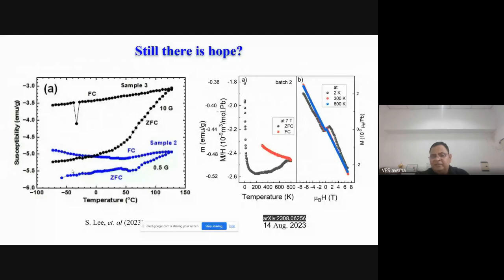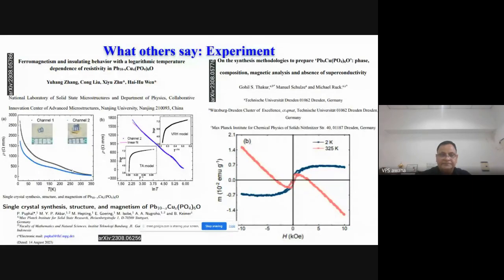In their M-T, M-H, and M by H with temperature, the magnetic susceptibility and moment both are shown. In fact, it's a system which shows diamagnetism. At the same time, it had some magnetic properties at low fields, which if you zoom at plus minus 1 Tesla, will show some sort of ferromagnetic component. Well, this was not the only case, more papers kept coming.